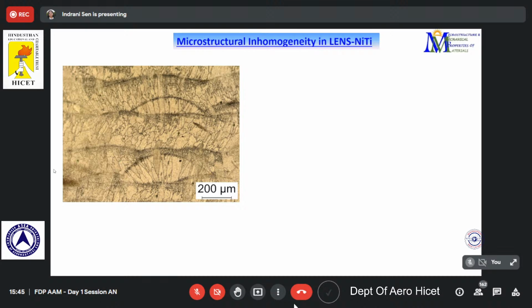Okay, so this is the optical microstructure, and you can see that these are the layers. You can see the layers very clearly, and within these layers we also have structures which look like a loop, and this is nothing but the way the laser has been tipped around. So this signifies the tip of the laser. The difference between these two tips is known as the hatch spacing, and we can also figure out the layer thickness from this. That is what we have done in detail. We have taken a montage of several images to figure out the layer thickness and the hatch spacing of the structure.